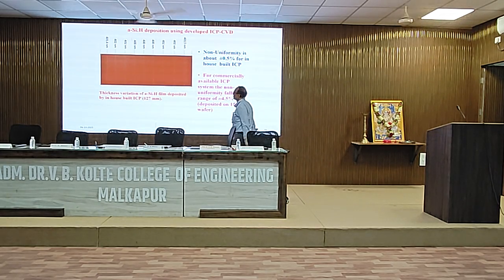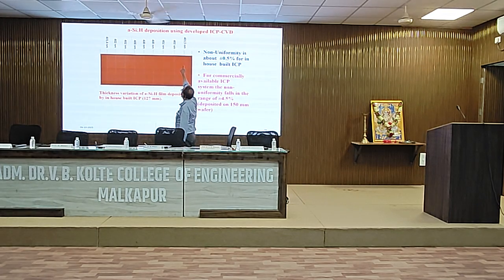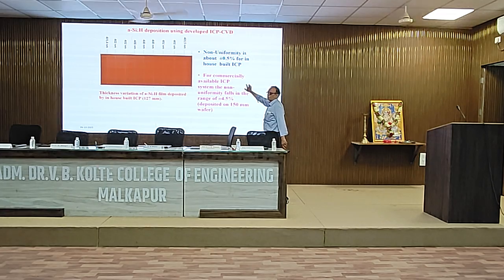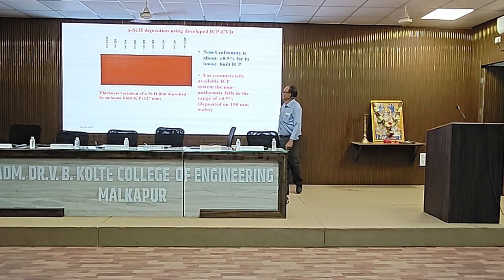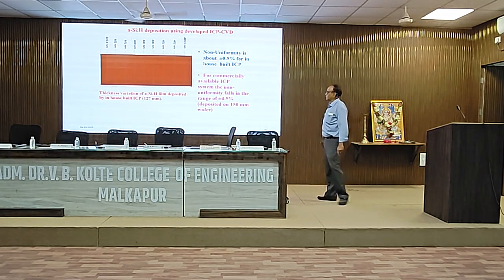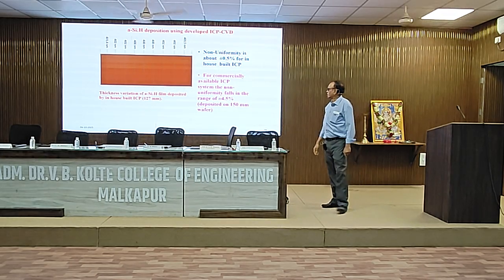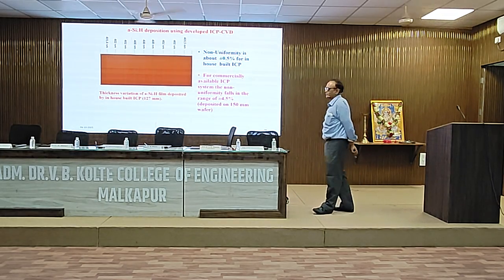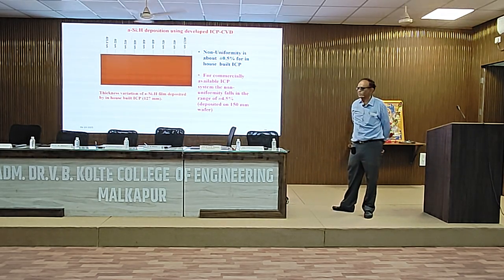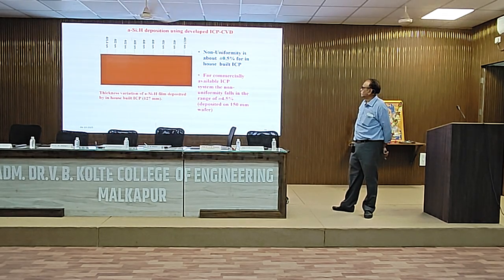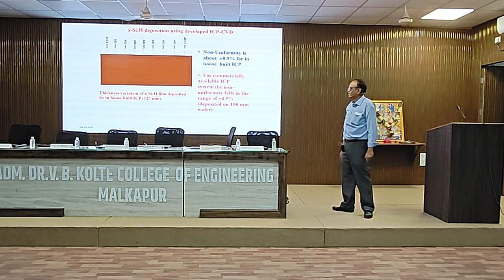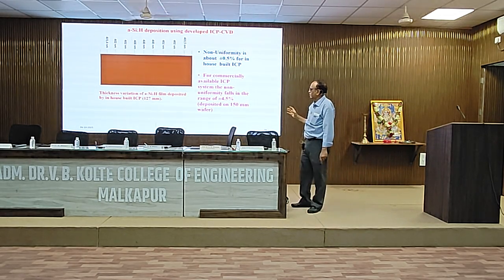Thickness was measured: 400 nanometer, 402, 401, 402, 400, 400, 400. Okay. Non-uniformity in the coating is only 0.5%. For commercially available inductively coupled plasma systems, the non-uniformity falls in the range of plus minus 4.5%. Our unit that we have developed is giving 0.5% for the facility that is developed indigenously. So this shows